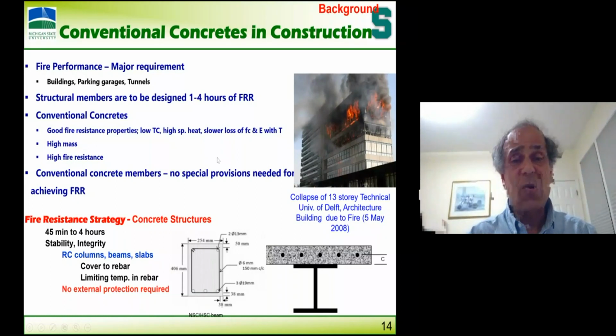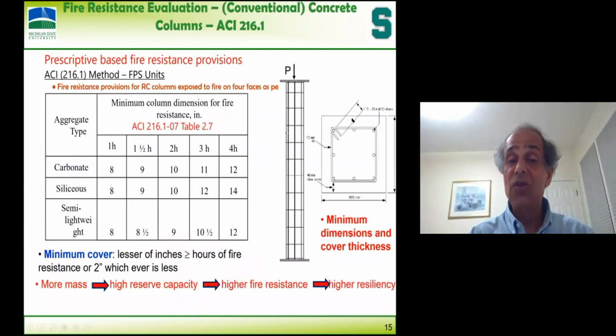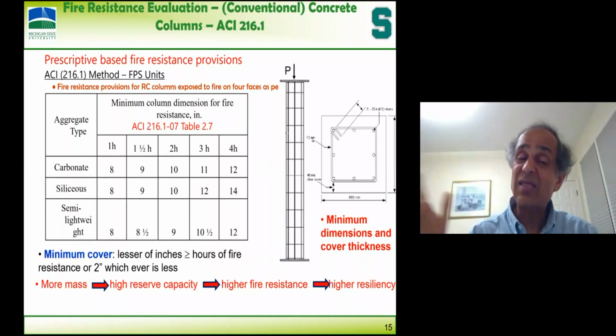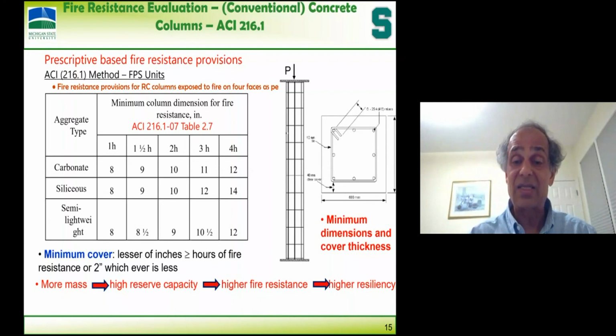Now, American codes are so prescriptive that there is no other way of engineering the system right now. For 1 hour, as long as your minimum dimension is 8 inches, that's 200 millimeters, you get 1 hour in a column cross section, and you need to provide 1 inch of concrete cover for getting a 1 hour rating. For 1.5 inch concrete cover, as long as your minimum dimension is 9 inches, you are going to get a 1.5 hour rating, and so on. As simple as that, which is not realistic.